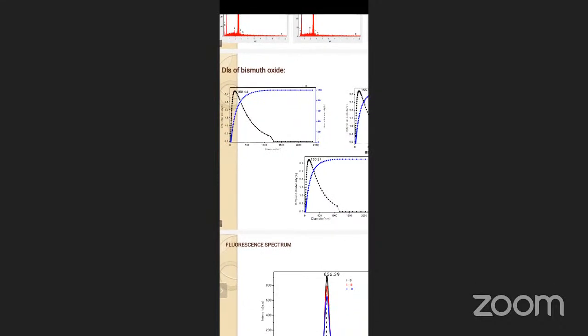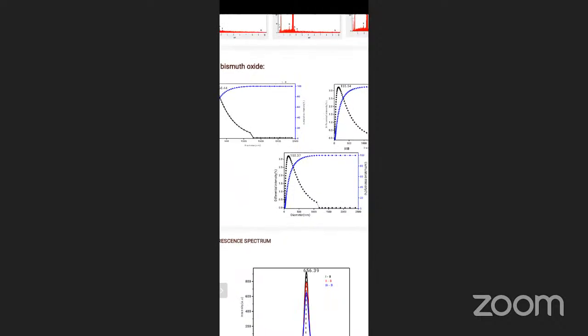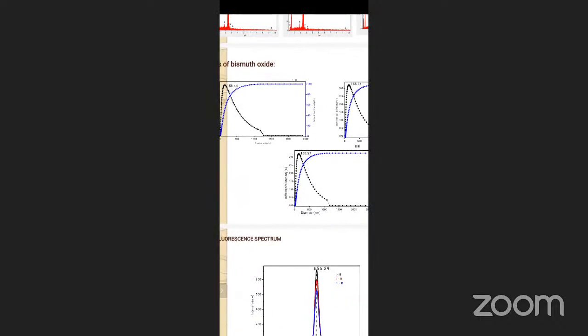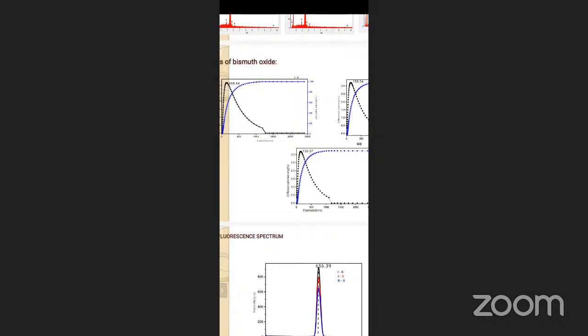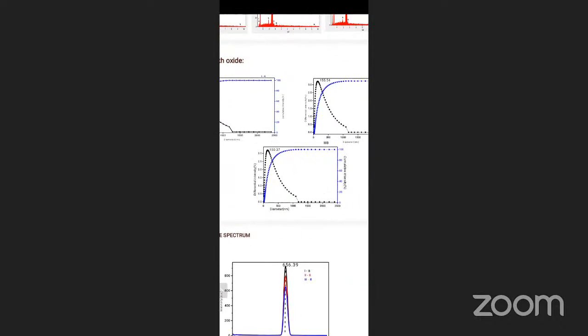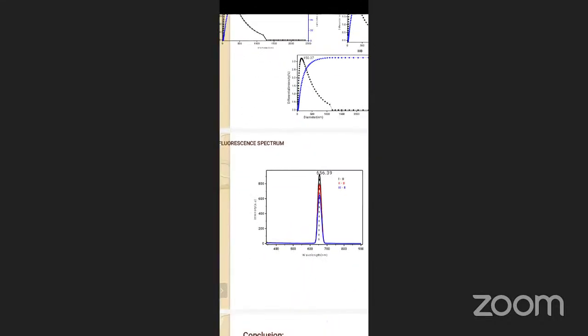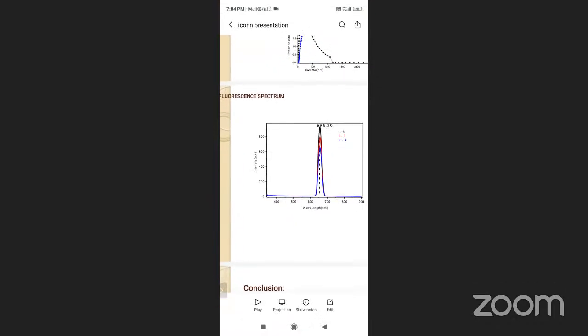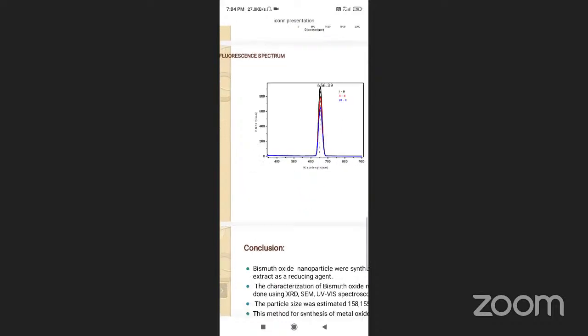In the DLS spectrum, we can conclude the particle size of the samples. In the three samples, the particle size is in the range of 150 to 160 nanometers. And then the fluorescence spectrum: the emission is at 656.39 nanometers in all three samples.